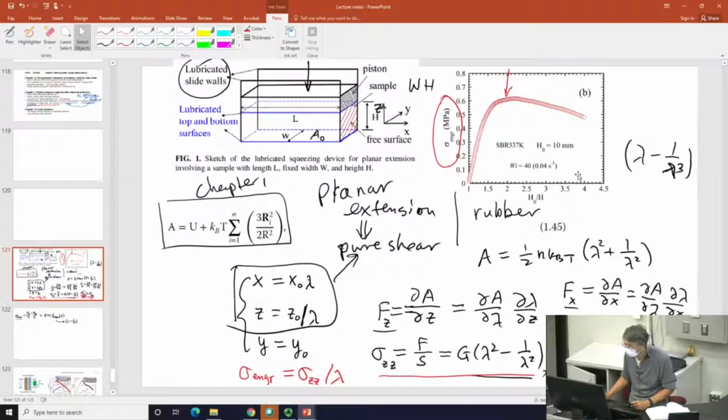So, okay, here you go. You squeeze by a factor of almost 4, for example. Quite a bit, right? You squeeze. What are you trying to learn? What we were hoping to examine is such a scenario where you have no free surface, where you terminate your deformation after a large amount of strain. And you're going to watch what happens during so-called stress relaxation. Keep in mind, during this stress relaxation, the sample will be incapable of becoming globally unstable, because the geometry constrained it will remain rectangular no matter what.